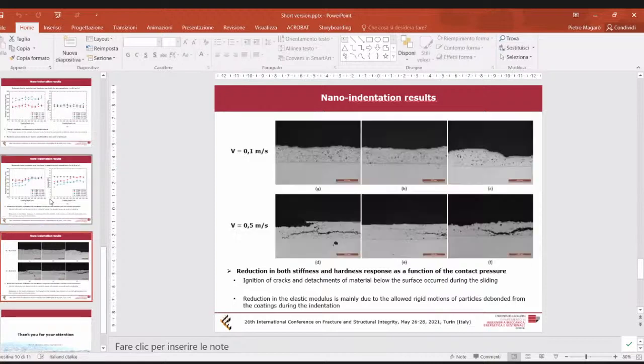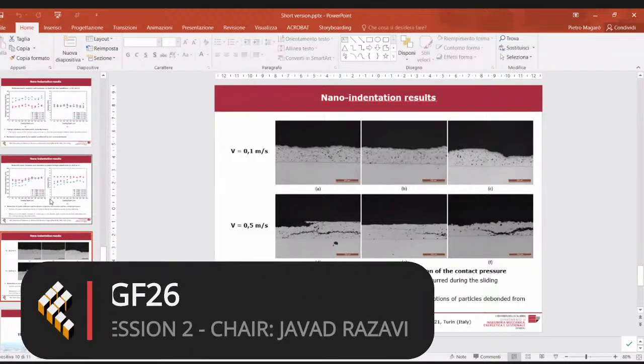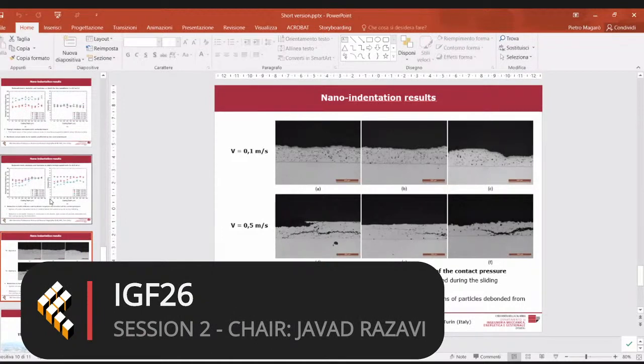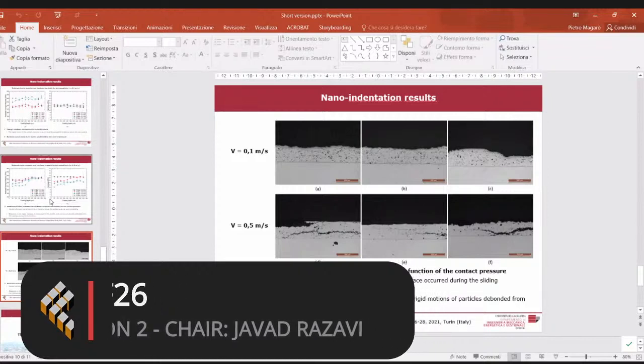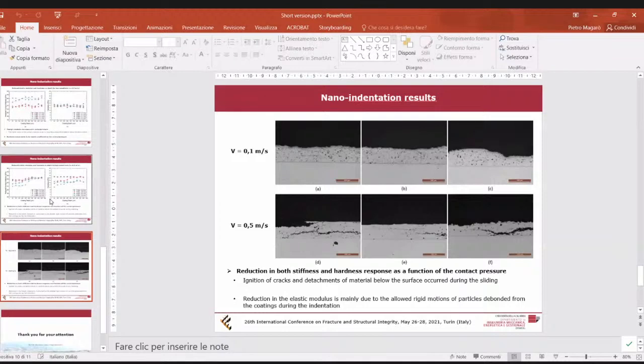Some cracking. But I think that the cracks are visible in the samples tested at high speed because the damage mechanism was mainly adhesive. But in the case of 0.1 meter per second, the main phenomenon is the pullout. So I think that crack ignition and propagation may have occurred also in the case of slow speed, but this propagation results in pullout. So the cracks are not observable in the cross section after the test, but it's possible to assume that the cracks ignite and propagate also in the case of 0.1 meter per second, with the pullout resulting as a consequence of cracks that propagate.